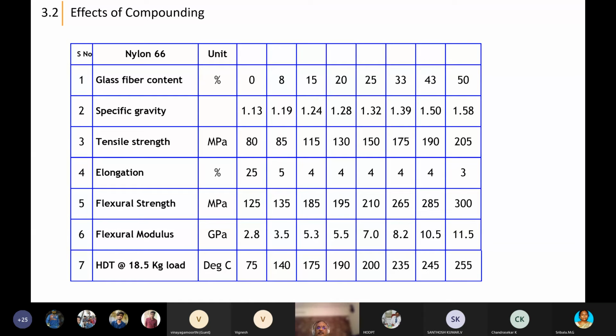The unfilled nylon has a specific gravity of 1.13, which goes to 1.58 when 50% glass fiber is added. And you see the tensile strength from 80, it goes up 2.5 times more. It crosses 200, but elongation drops, which means the rigidity goes up. Flexural strength goes up. Look at the modulus. Modulus in gigapascal. Modulus is representative of the rigidity, how stiff it is. From 2.8 gigapascal, it has gone up by 4 times, 11.5 gigapascal in 50%. If you try to break the specimen of 30% glass reinforced nylon 6, your hands will get a shock, the energy shock. Anybody who is doing testing of it will understand that. So much is the energy.